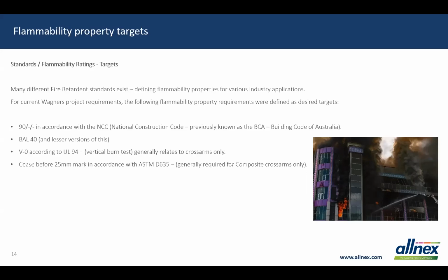And this is typically designed or intended for specified protection of buildings from catching fire as a result of wind or airborne embers. So it addresses that situation. The classification qualifies these composite materials for fire situations involving increasing levels of ember attack, burning debris by wind-borne embers, and combined with a heat flux limit of up to 40 kilowatts per metre squared, they've defined. Also it's to account for where there's an increased potential for exposure to flames in the application. The UL94 and ASTM D635 are quite similar vertical and horizontal burn tests respectively. UL94 V0 ratings are very commonly understood throughout the fire retardant composite applications in the industry.